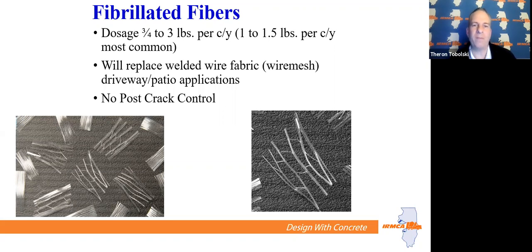But the problem with welded wire fabric is if a crack starts at the top of the pavement and starts to travel down to the bottom, it's going to keep opening up till it actually hits the welded wire fabric at the bottom of the pavement. So that crack's going to open up and it's going to get wide. But with fibers, they have the same responsibility. They don't stop cracks from happening, but they hold them together once they happen. With fibers, the fibers are from the top to the bottom of the pavement. So when a crack happens at the top of the pavement, it immediately hits a fiber and it can't open up anymore. So it's not as unsightly, doesn't open up as much, and it's a much better concrete pavement with fibers compared to a welded wire mesh.